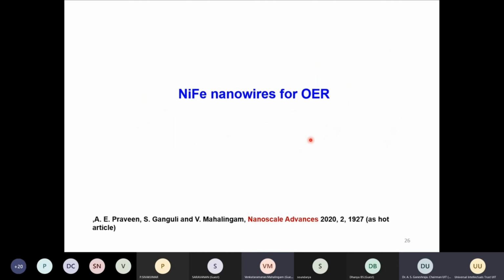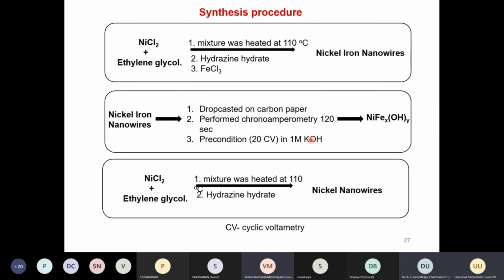So I think in the rest of the talk, I will concentrate mostly on catalysts which are used for the oxygen evolution reaction. As I mentioned before, it's quite challenging compared to the hydrogen evolution reaction. So we tried to prepare nanowires. The idea here is how to increase the surface area of this catalyst so that several catalytic active sites can be present on the surface of the material. With this idea, we tried to prepare these nickel iron nanowires.